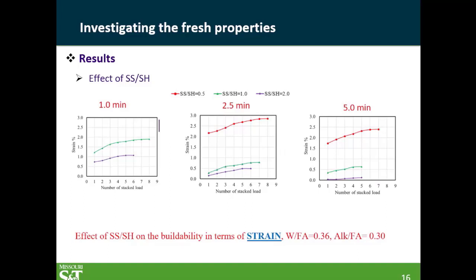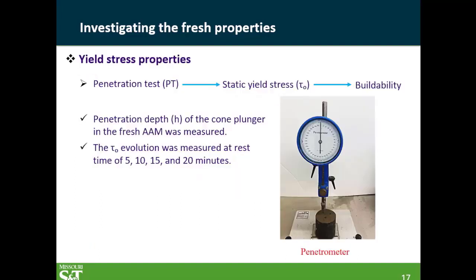So along this line, as I mentioned at the beginning, we looked at different parameters. We looked at the sodium silicate to sodium hydroxide ratio, and related this again to the cycle time and the strain on the layers. Well, for the yield stress evolution, we would like to also look at an easy to do test.